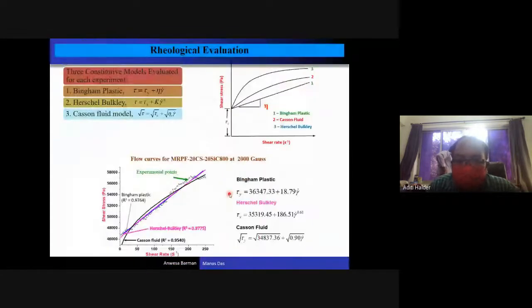If you plot the shear stress and shear rate values at different shear rates, you will get different points. These points can be fitted using different curves. We used three different models: Bingham plastic, Herschel-Bulkley, and Casson. Using these three equations, we calculated the yield stress and viscosity of this fluid. Like this, you can measure them.